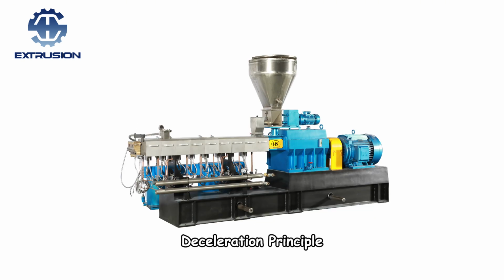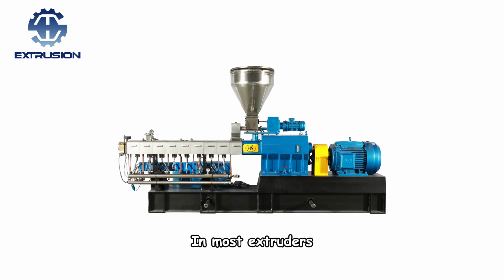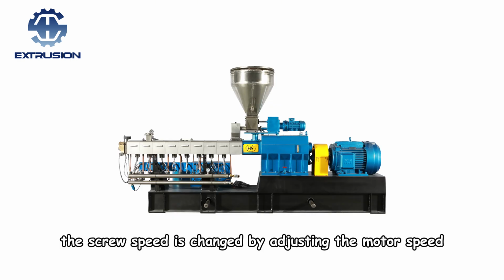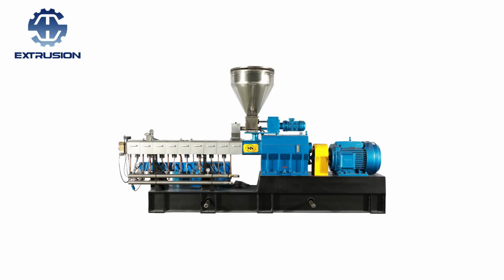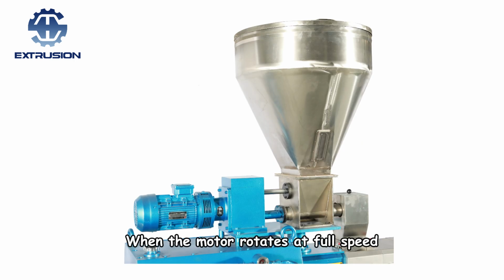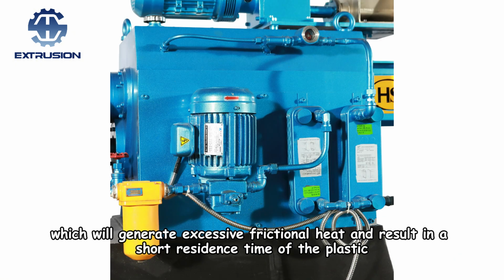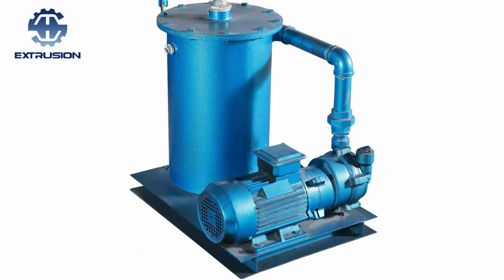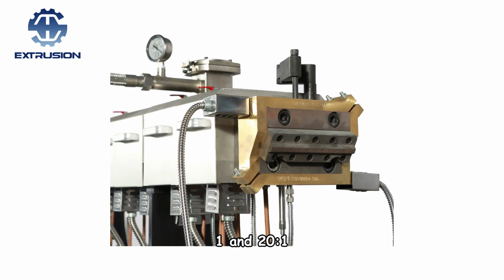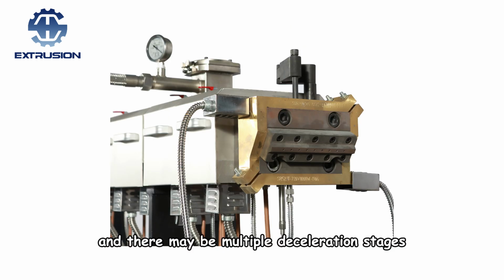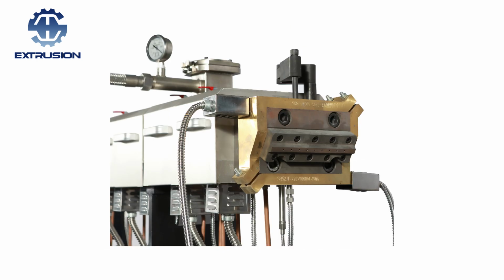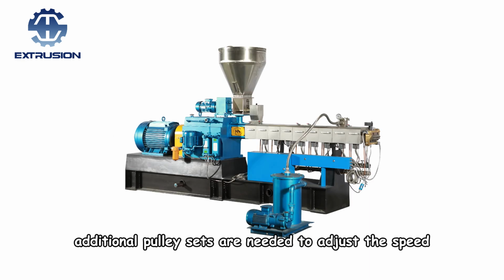3. Deceleration principle. In most extruders, the screw speed is changed by adjusting the motor speed. When the motor rotates at full speed, it is too fast for the extruder screw, which will generate excessive frictional heat and result in a short residence time of the plastic. The typical reduction ratio is between 10:1 and 20:1, and there may be multiple deceleration stages. Sometimes, additional pulley sets are needed to adjust the speed.